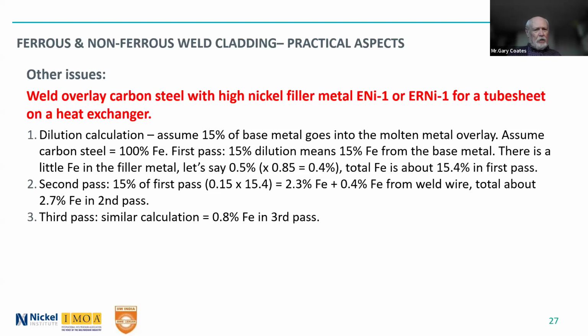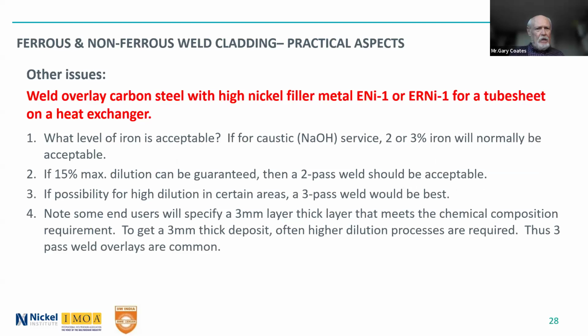Some people may want a third pass. You get only 0.8% iron in the third pass. So you have to say what level of iron is acceptable for that particular job. If it's caustic service, normally 2 or 3% iron will be acceptable. If you can guarantee 15% dilution, well, then a 2-pass weld should be acceptable. But if you're not sure that you're going to get 15%, it could be higher. You really need to think about that.